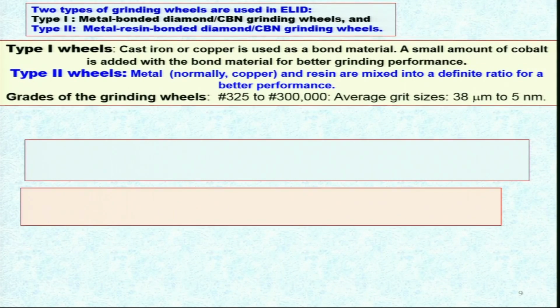Now, grades of the grinding wheels, 325 to 300,000. Average grit size is 38 micrometer to 5 nanometer. These are very fine abrasive particles, these 5 nanometer abrasive particles.